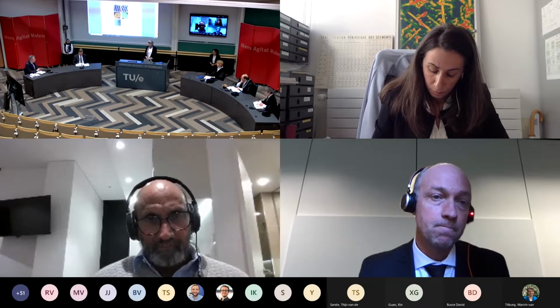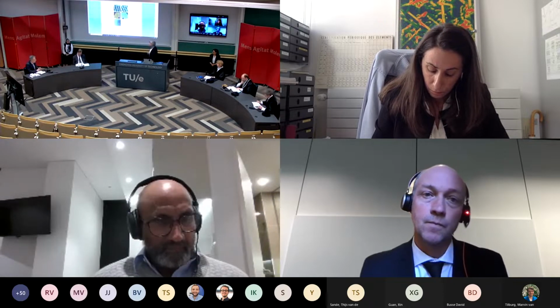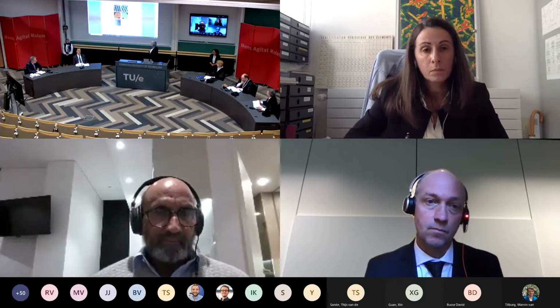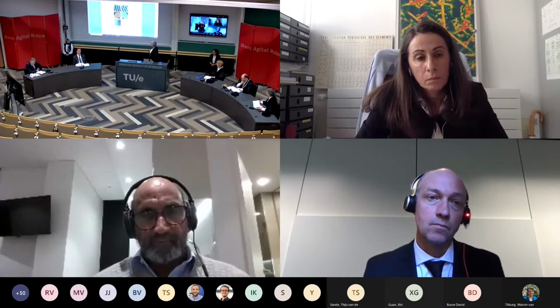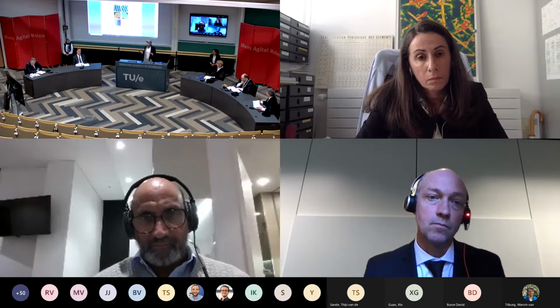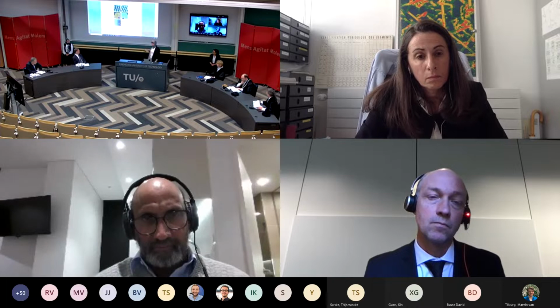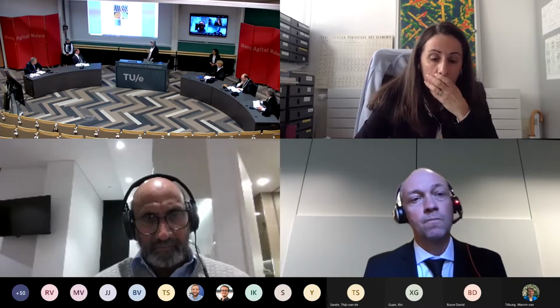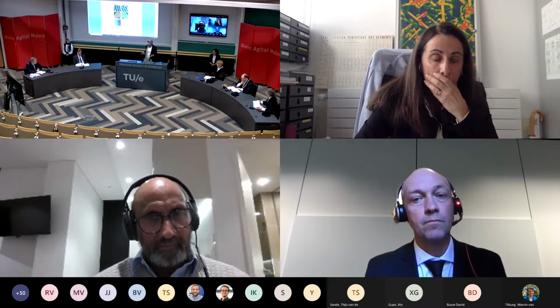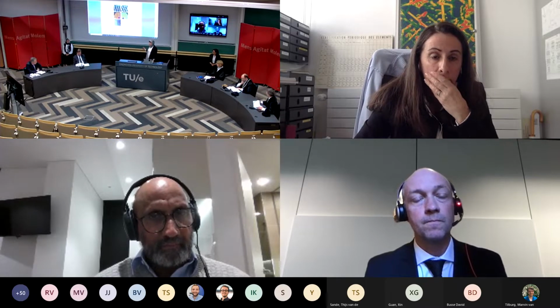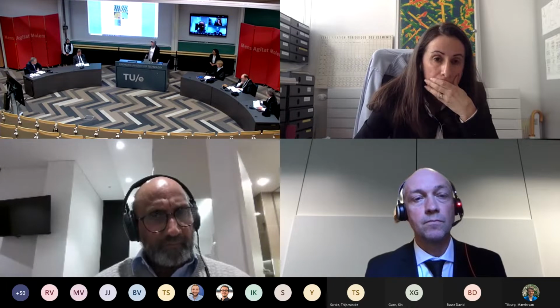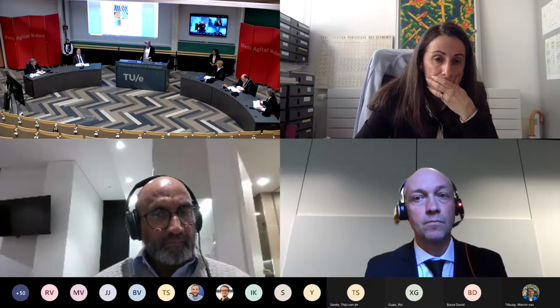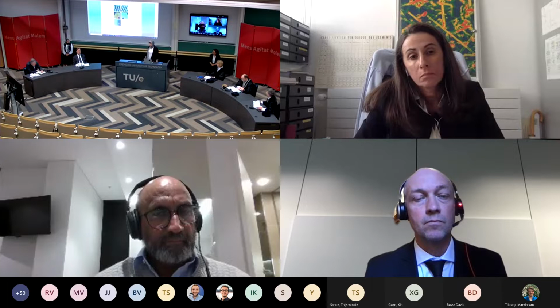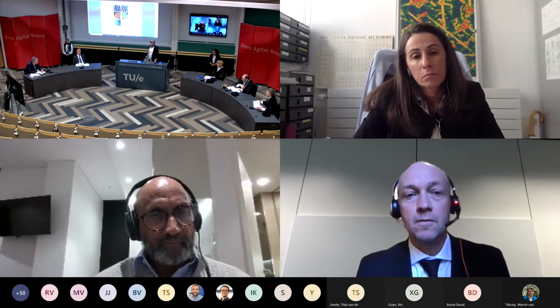To the opponent, thank you so much for this question. We actually thought about it, and if we look at the mapping or the line profile across the composition of our shell, we will see there is a variation of 3 to 5% in the alloy composition. And this is almost the same percentage in our sunburst region. So we can say that the enrichment in our sunburst region is already within the alloy fluctuation in the whole structure. So I would say they are very thin until now, and they are not really detrimental to our optical properties. However, in the future, they might be utilized as quantum wells if we engineer it properly, for example, if they are germanium rich. And there are already publications about that.